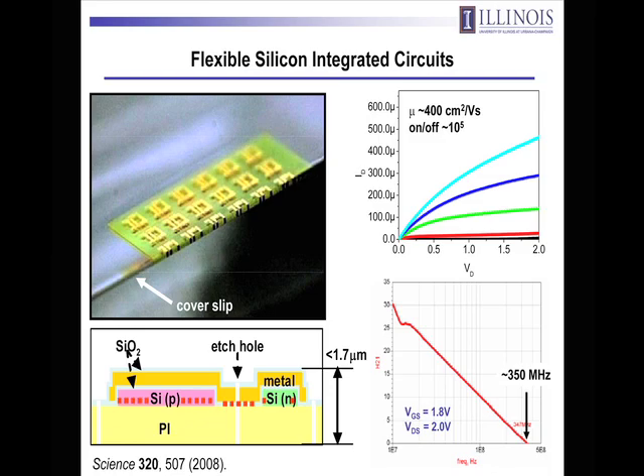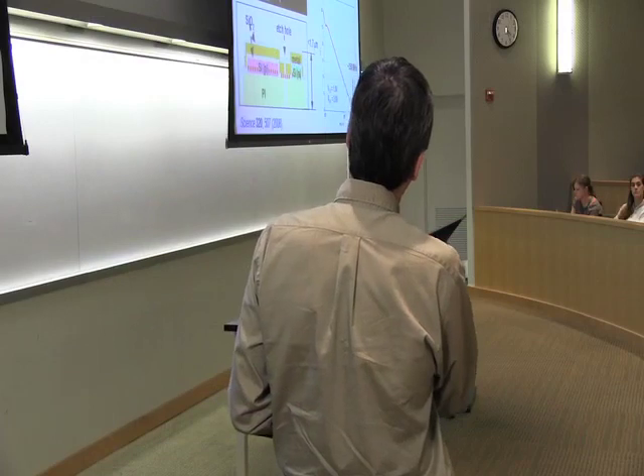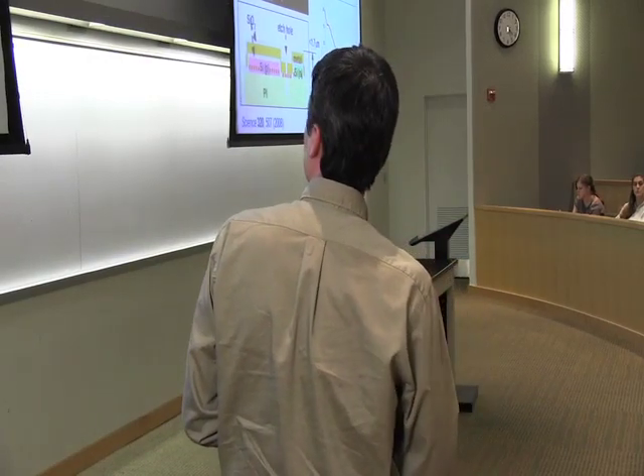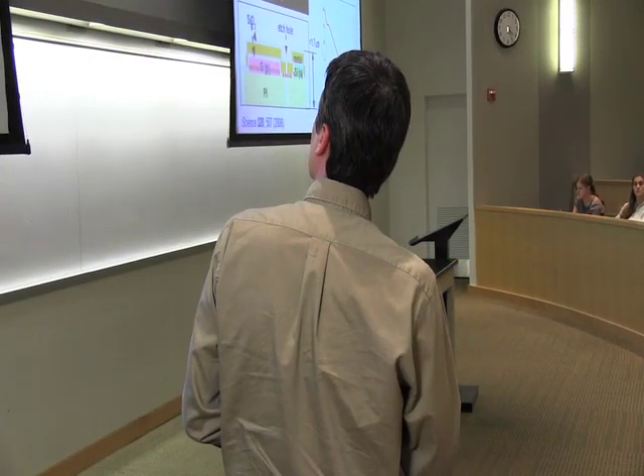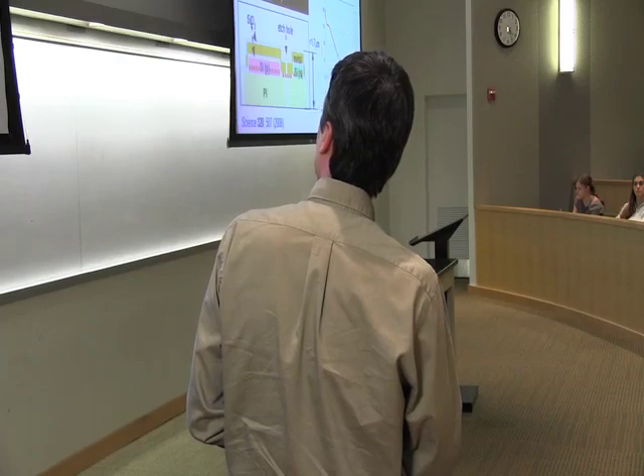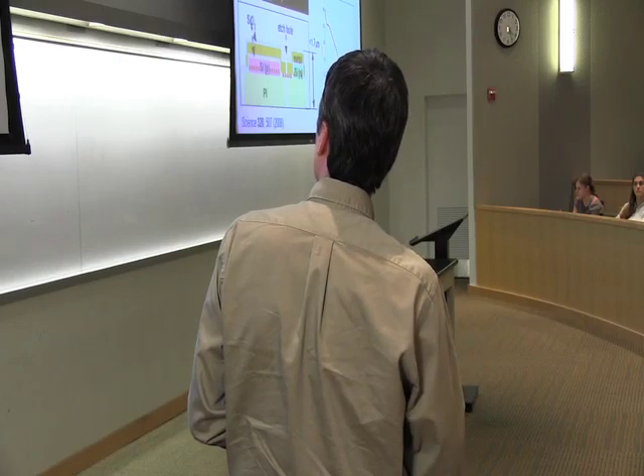It's a little bit more complicated here because you have different materials with different mechanical properties, but you can compute where it is and choose the thickness of the polyimide, again, such that you get that neutral mechanical plane overlapped with the silicon. So if you do all those things, you make it very bendable, and at the same time, you have individual device characteristics that, at least in our hands, are similar to otherwise similar designs that you would build on an SOI wafer substrate, but with this kind of mechanics. So mobility in the range of 400, on/off 10 to the fifth. That could be a little bit better, but that's what we get.